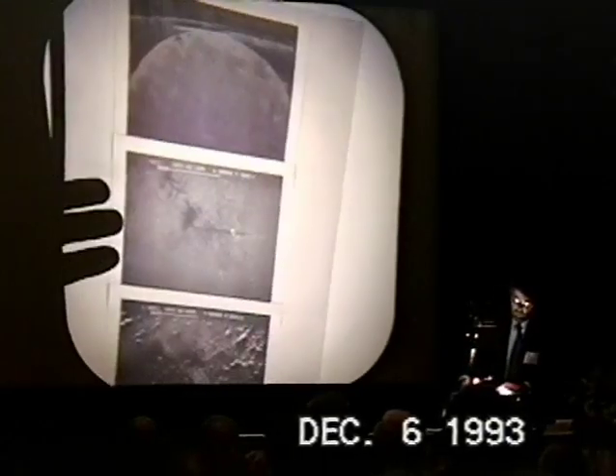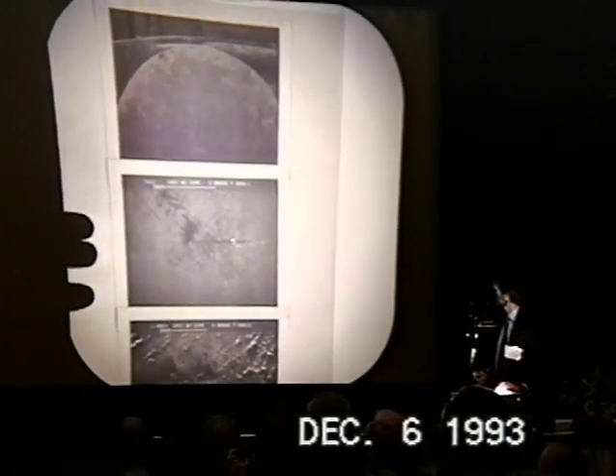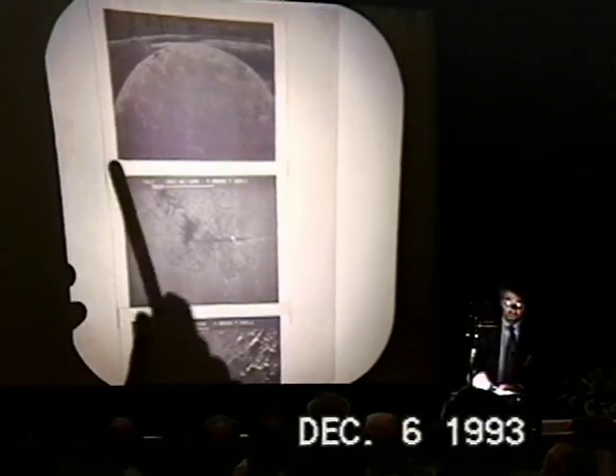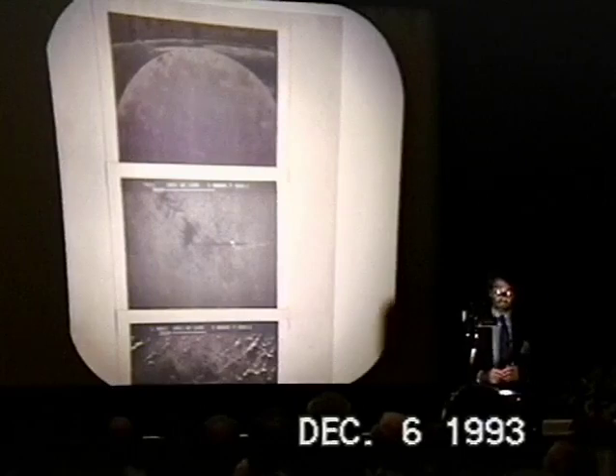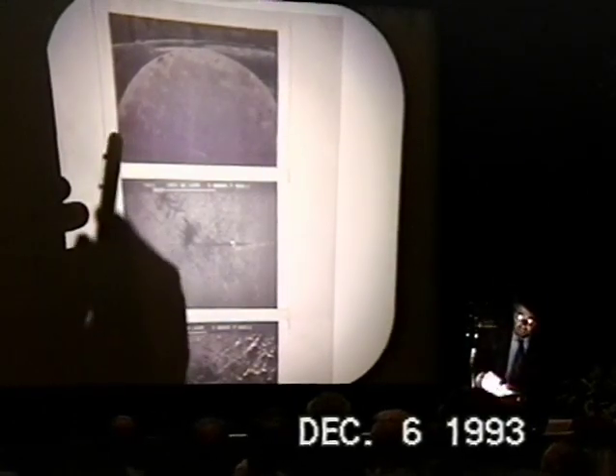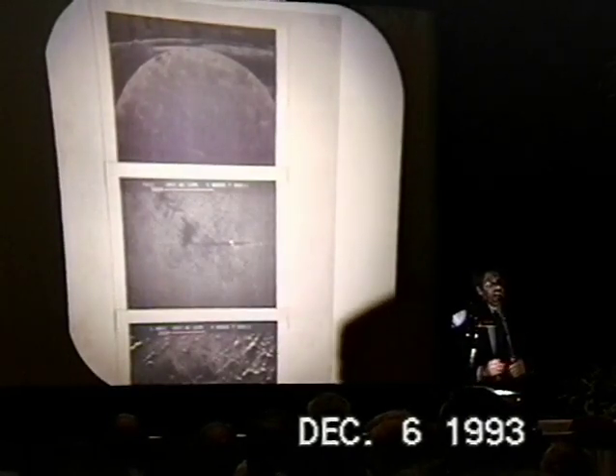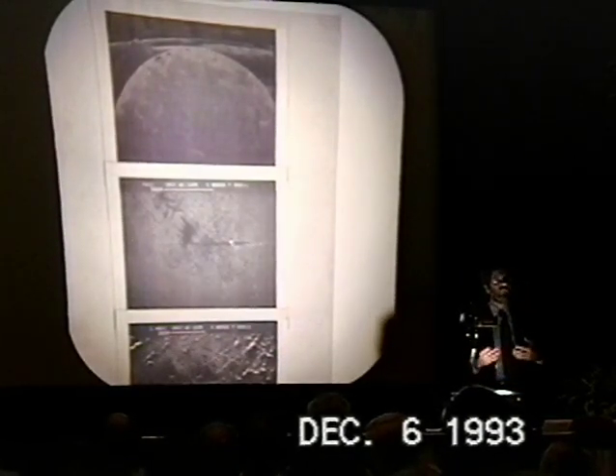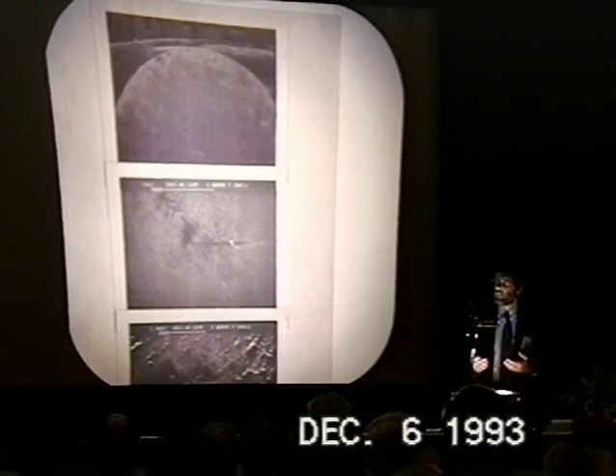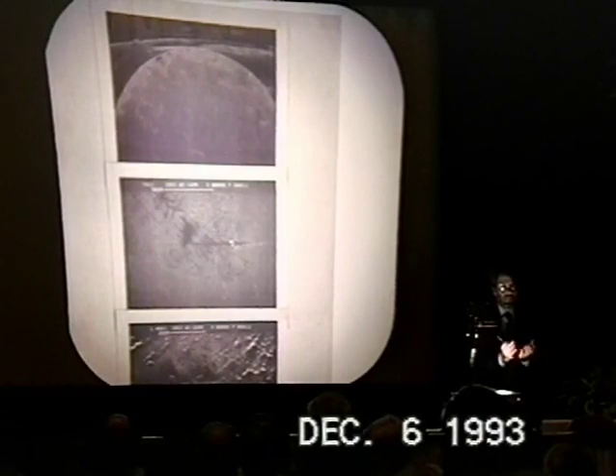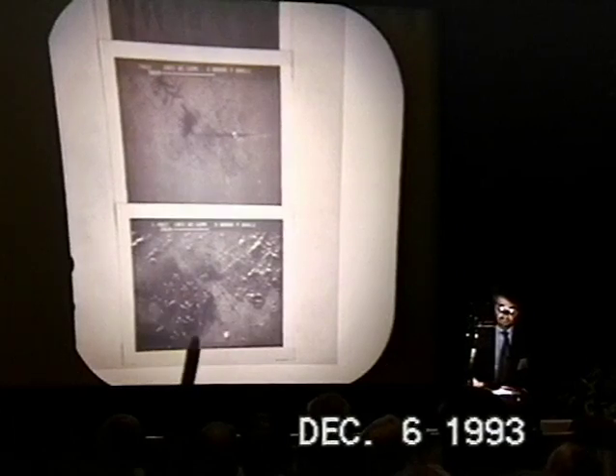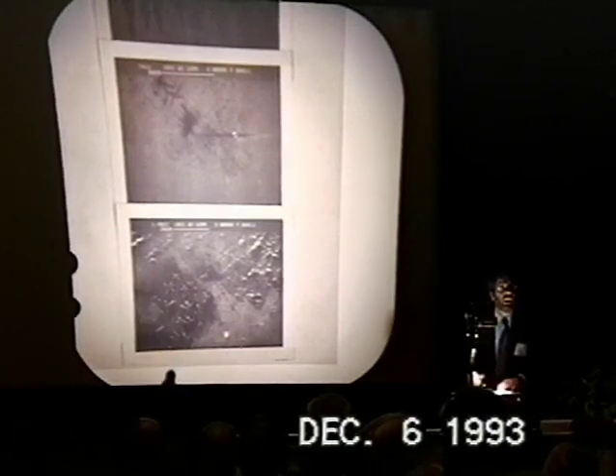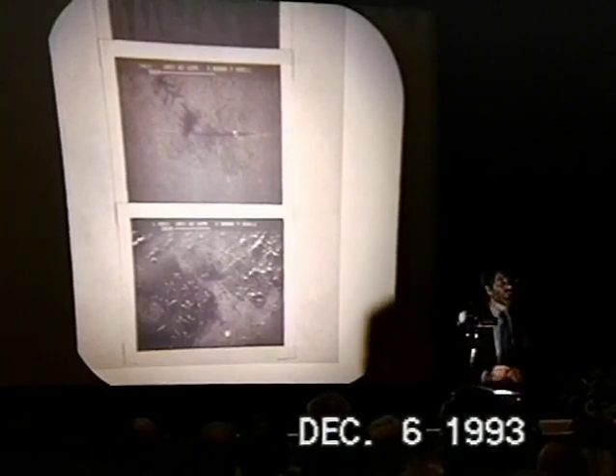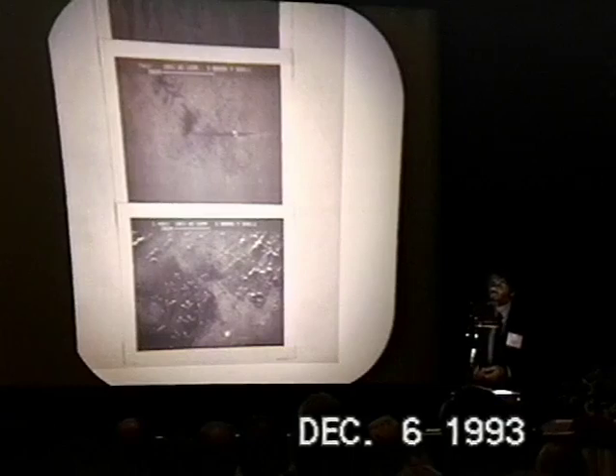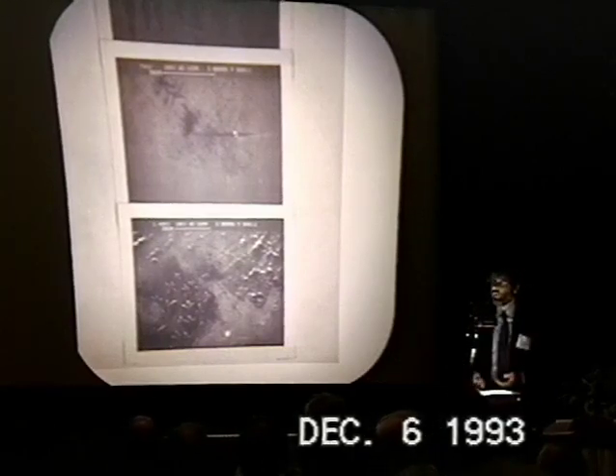Just to finish, I want to show you some scanning electron microscope images. This is a cross-section of an electrode which underwent a confinement experiment. As you can see, there is a corona in which there is a massive effect of the nucleation of another phase. At present, we cannot have an analysis of this corona, but it's important to see that there is an island of nucleation, dendritic nucleation, which is typical of high concentration of deuterium and the precipitation of deuteride.